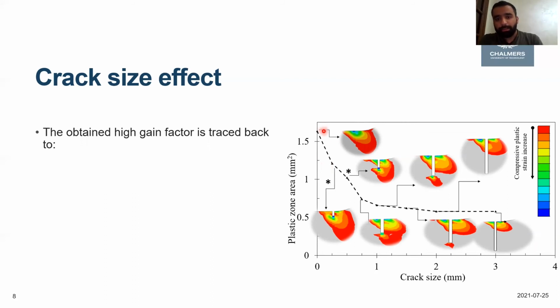Here is a figure from another publication, which shows that when the crack size increases, the plastic zone area introduced by HFMI treatment decreases. But for crack size less than 2 millimeters, we can get a compressive plastic zone area around the crack tip, which is very favorable and good for arresting the crack. So that gives us an understanding of why we get good fatigue life extension.